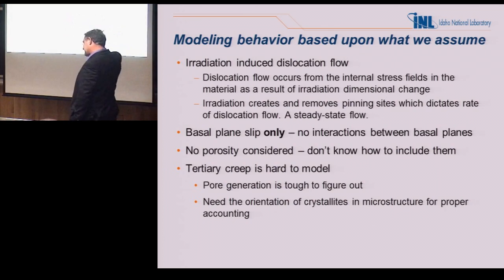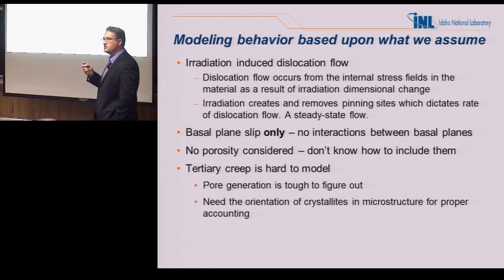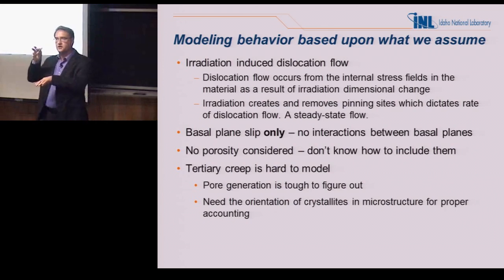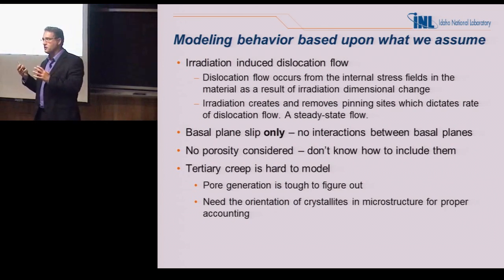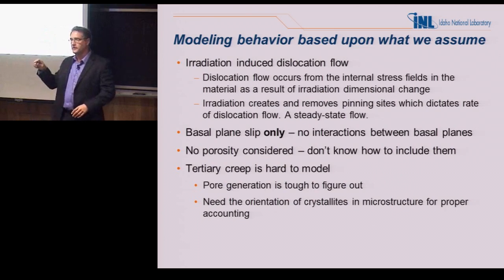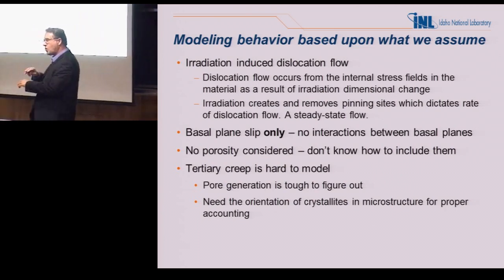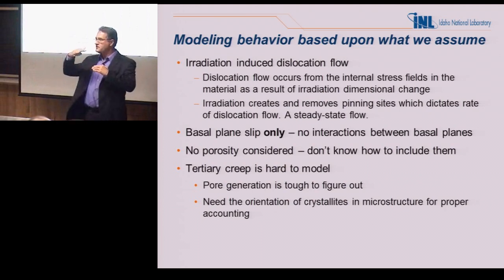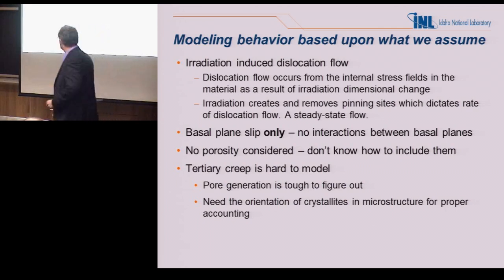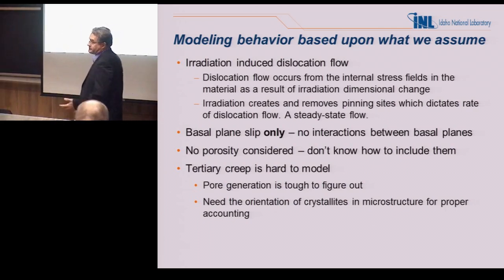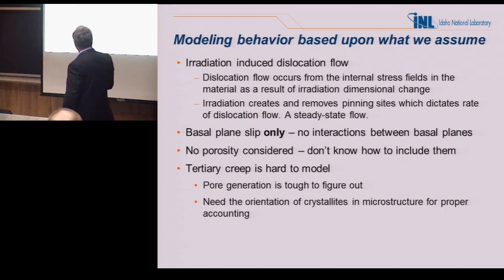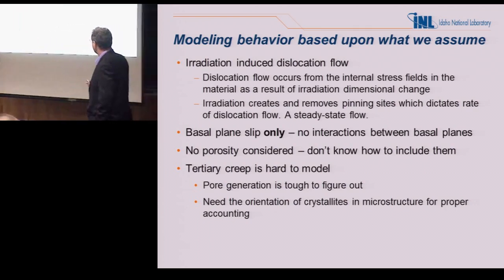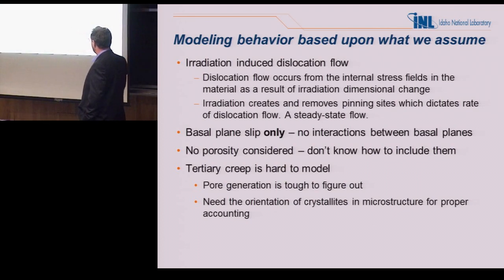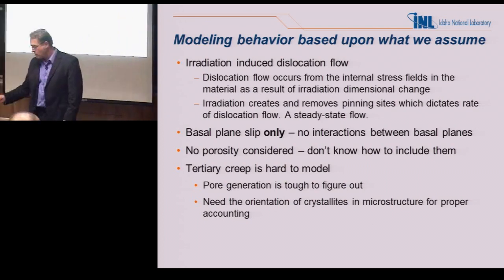The assumption, though, is that we don't understand what basal planes are doing. It doesn't make any sense. They don't talk to each other. They don't communicate because it's weak van der Waals forces. It's only within the basal planes. So that's why we came up with this pinning, unpinning. It's only in these basal planes. It's a one-way street. There's no dislocation climb like you have in metals, we thought. No porosity considered. It's hard. And then tertiary creep, of course, is very hard to predict because of the pore generation and the need for the orientation of the crystals and the crystallites to understand how it's actually deforming over time.